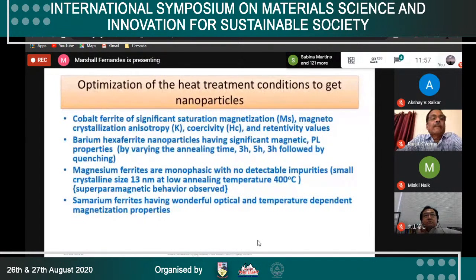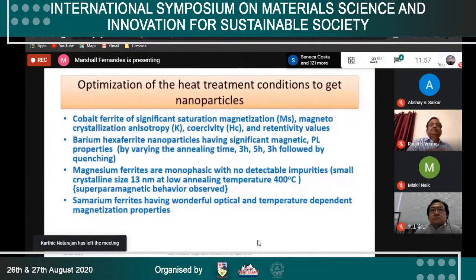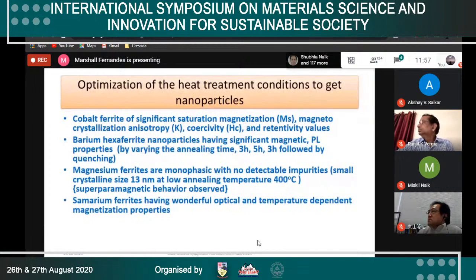So after synthesizing the particles, preparing the citrate precursor, heating it, annealing it, or quenching it, we go for studying its electrical, magnetic and optical properties, and for structure analysis, electron microscopy, and before that XRD, Rietveld, and other analysis. After these studies, we can get the best particles, and we can put those particles to use for technology.